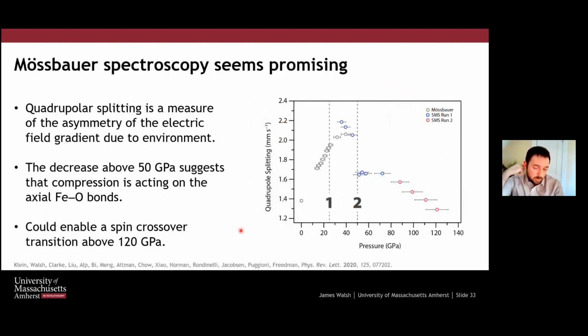And so from the Mossbauer, I told Erjan at the beginning that we would have some data. There's so much more data behind the scenes. I'm really condensing it into one picture. But this is showing the quadrupole splitting that we get from Mossbauer spectroscopy as a function of pressure. And the quadrupole splitting is a measure of the asymmetry of the electric field gradient, which is due to the asymmetry of the environment.